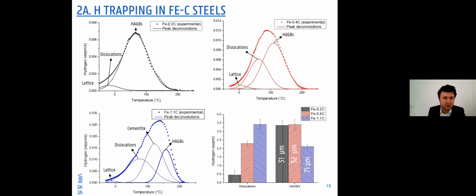So here you can see the deconvolutions of the TDS data for the 0.2, 0.4 and 1.1 carbon steel. And we can make this deconvolution. And then you can see that we have several peaks available, one from dislocations and the high angle grain boundaries, and also for the 1.1 carbon steel, we have a peak linked to second phases. This is not that straightforward. A lot of tests are done, a lot of repetitions are produced, and of course, different heating rates are needed to calculate the activation energy of the trapping site.